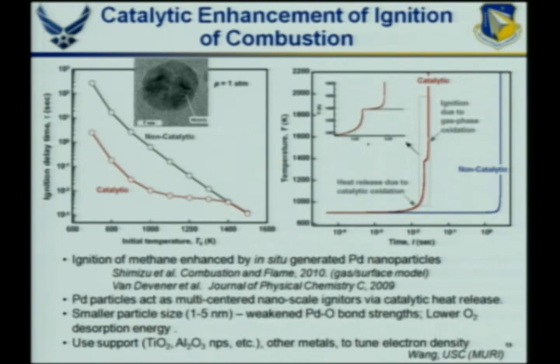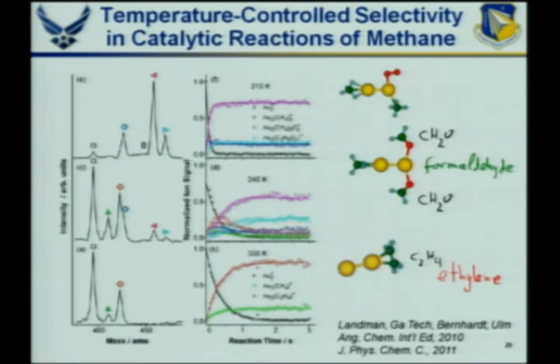So they perform some catalytic chemistry, it releases heat, and then you see this bend in the curve. That heat that's released from the catalytic process then ignites the gas phase chemistry that goes on. So we're trying to understand some of these mechanisms of how these catalysts work to get this jump started. And again, we'd like to be able to make this work at even lower temperatures, and the key again is this binding energy. If you can weaken this palladium-oxygen binding energy, you can make this go even faster. So we're looking at ways to do that with different supports, different ways to control the electron density.